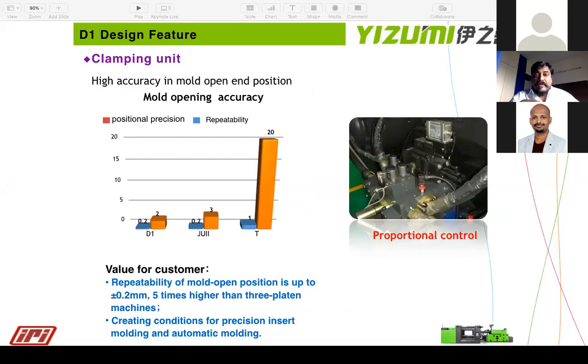Then also the mold opening and closing accuracy: since we use individual proportional valves for the tie bar positioning, and also a separate proportional valve for mold closing and opening, it has very high repeatability. We can guarantee less than 0.2 mm. Okay, if you see a typical toggle machine or the ram machines, it varies between 1 to 1.5 mm, or maybe 0.5 mm in the best case. But here it will be around 0.2 mm. We can guarantee that on the position of the platen.